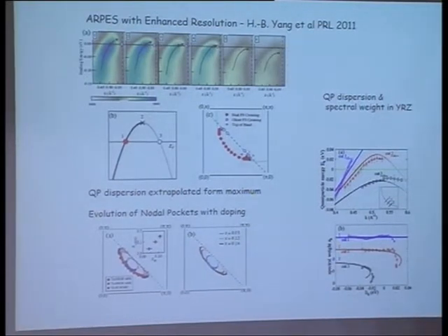When you go through the maximum in the Bogoliubov spectrum, you lose weight rapidly as you cross the maximum. So the form that this pairing form shows has exactly this weight loss, and so it's very nicely consistent with these ARPES data. And this shows the area of these pockets and the relation of that to the doping. It scales nicely with the doping.